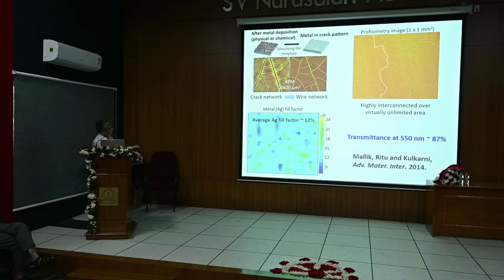You can even map them by using various techniques, and you can calculate also what kind of fill factor you have achieved after putting the metal. So in this case, silver, which we have done up to 12%, that's the fill factor. We want to keep the fill factor low because we want a lot of light to pass through the glass piece. At the same time, it should be electrically conducting. So we achieve transmittance in the visible range to the tune of around 85-87%.